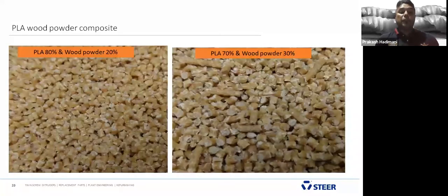We did a similar study for PLA, polylactic acid, with wood composite at 20% and 30%. We could manage the compound, but unfortunately, when it went to injection molding, we could not make injection molded samples. Maybe we need to go for compression molding and other studies. It didn't flow in the injection molding. We are planning to understand why it is not flowing, maybe due to the viscosity. The compounding is not an issue, but for molding, we were not able to make it.